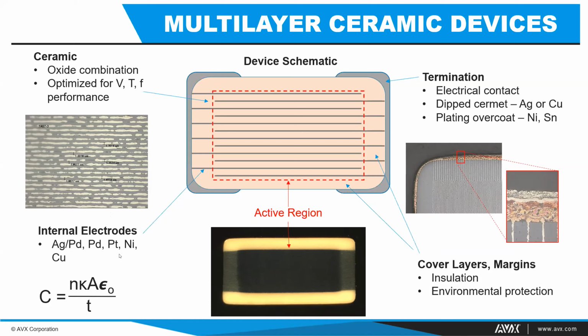electrode portions as well. Our internal electrodes traditionally were made of precious metals such as silver, palladium, platinum, and palladium itself. More recently, probably the past 2 decades, has seen a great climb in nickel and copper, and the bulk of the consumer grade parts, and often some of the more high performance devices are actually being used or made from those materials right now. But there is a significant difference still in precious metal parts, and there is a business available for those devices too.